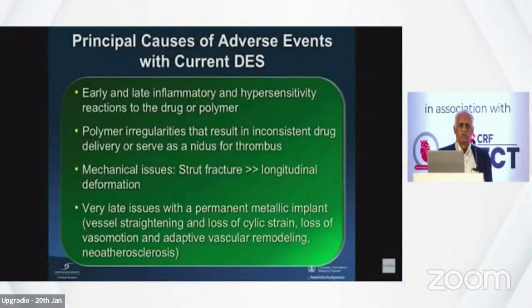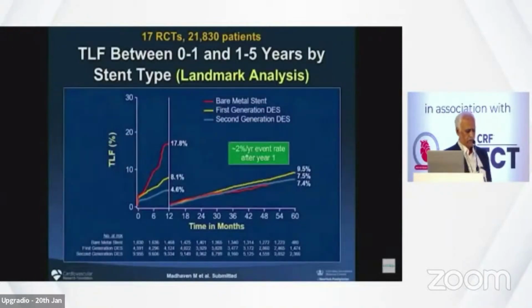Now, what are the causes of the main problems with drug-coated stents? Early and late inflammatory hypersensitivity reactions, polymer irregularities that result in inconsistent drug delivery or a nidus for thrombosis, mechanical issues like strut fracture or longitudinal deformation, and very late issues with permanent metallic implants, like vessel straightening and loss of cyclic strain, vasomotion is not there, and prone to neoatherosclerosis. This was mentioned earlier. In the first 1 year, you see much better results with the drug-coated stents, first generation or second generation, compared to the bare metal stents.